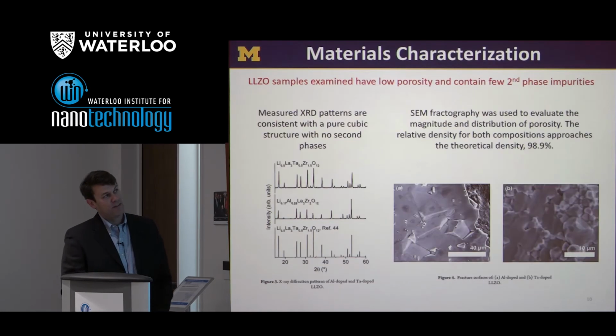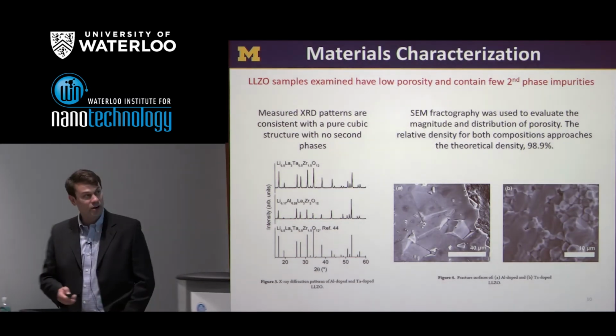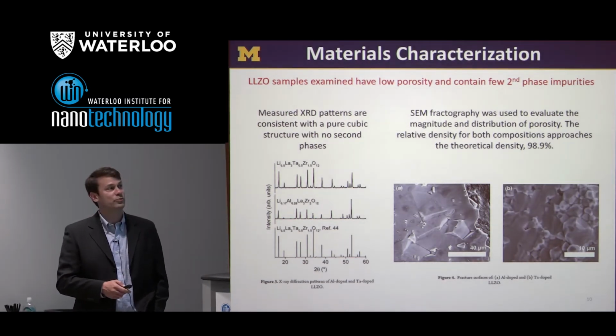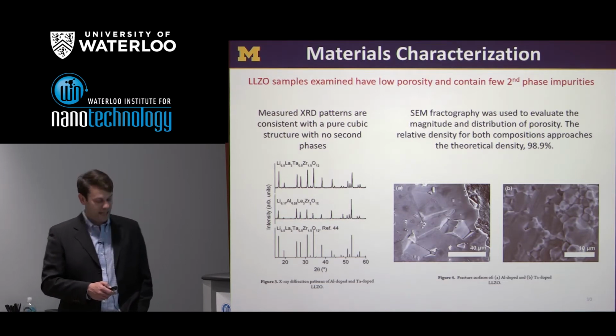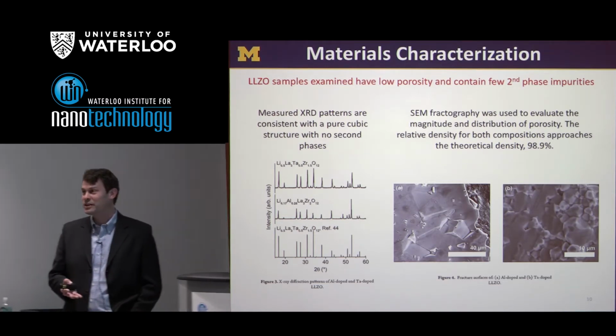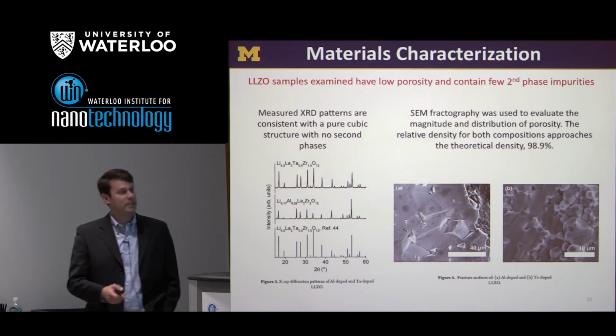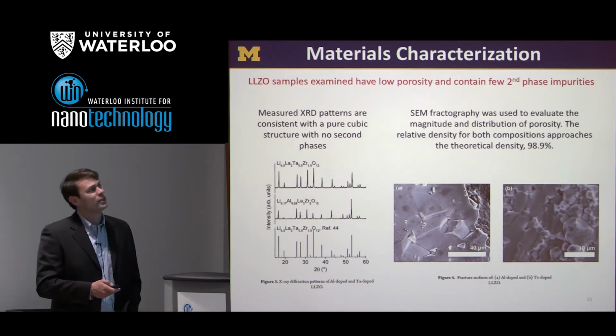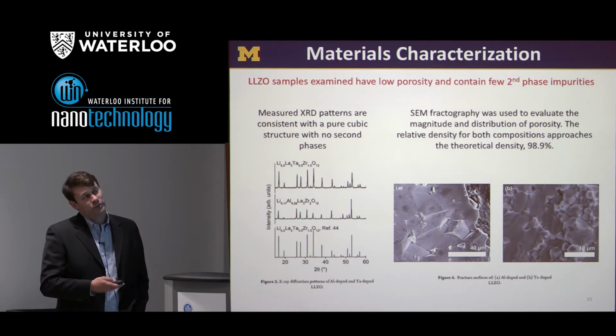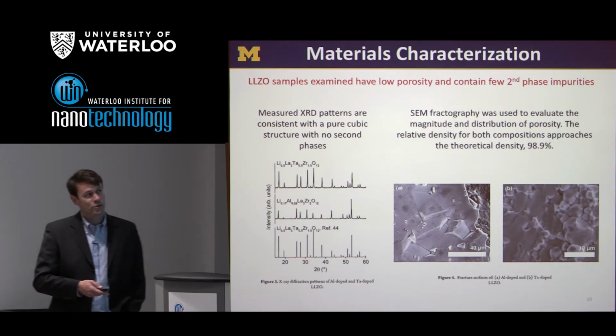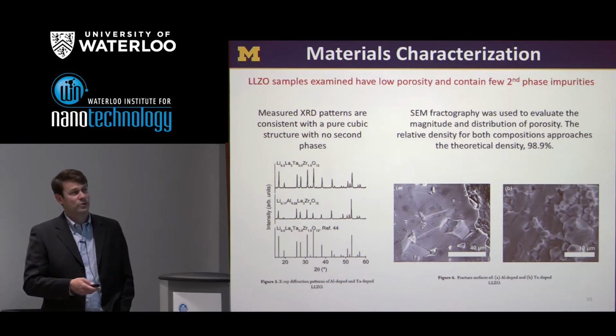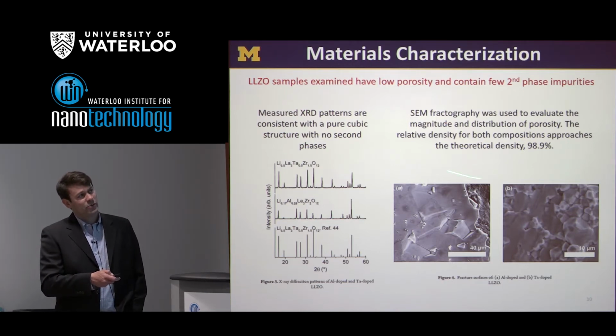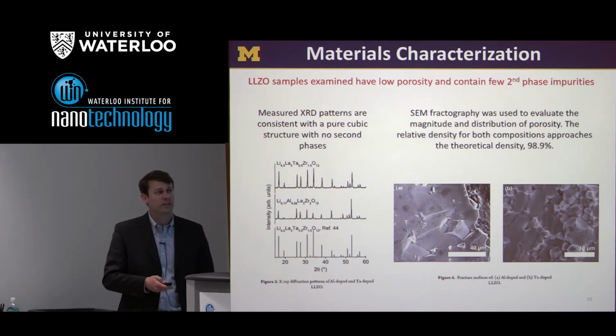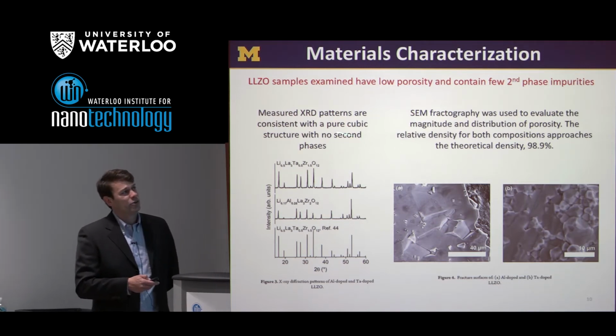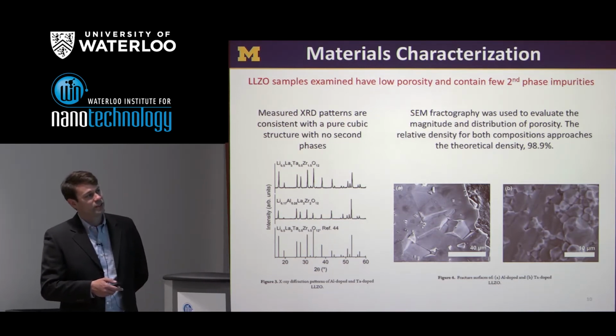So with this data, we have basically enough now to report our calculation results, but let me take a step back and show you some of the experimental data and why it's related or can be compared to our calculations. So our calculations are done on a single crystal, there's no defects, and a real material, of course, doesn't have those properties. But what our experimental collaborators are able to do is make very phase pure LLZO with very low porosity and with rather large crystallite grains. So you can see here on the right, this is some SEM fractography for a sample that was almost 99% of the theoretical density, so very, very low porosity. Also little evidence of second phases present in this compound.